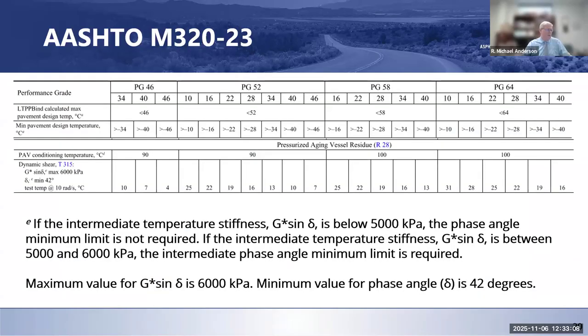But that led to some of the concerns about how to have something a little bit better. Ultimately, that's where this came in. This was a revision suggested through the task force of the Asphalt Institute Technical Advisory Committee, along with some work done within the binder expert task group, to look at intermediate temperature stiffness, what the phase angle would be, and how you might allow something that seemed a little bit stiff, but otherwise had good viscoelastic properties. That was through the use of a minimum phase angle overall. There were a lot of things looked at to try and reduce the variability, including using larger plates and reduced strain levels. Those were all things that were being done.